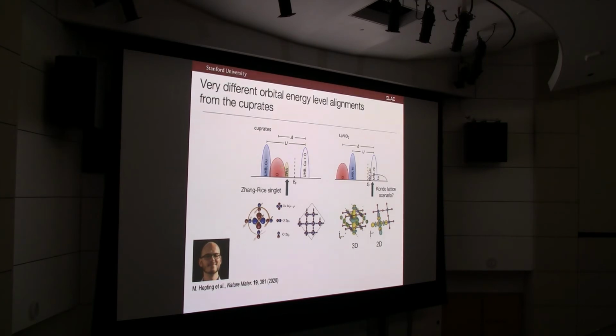So when you hole dope the system, an early idea was the notion that you have a strong Zhang-Rice singlet formation, which is a nice picture. Namely, because of this alignment, especially this oxygen 2p band, the nature of the holes is actually not purely copper-like, but really resides in this oxygen ligand field. And so this gives you both an overall singlet and a nice, interesting connection to antiferromagnetism and its fluctuations in this square planar lattice.